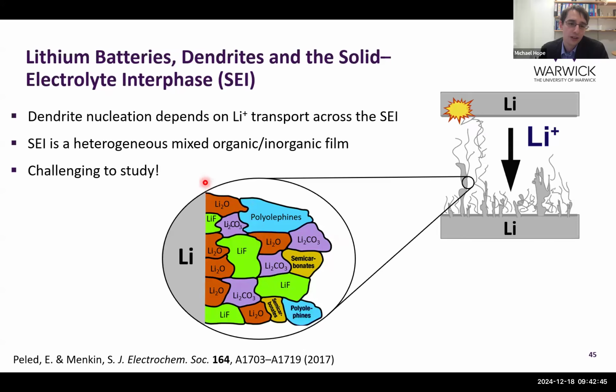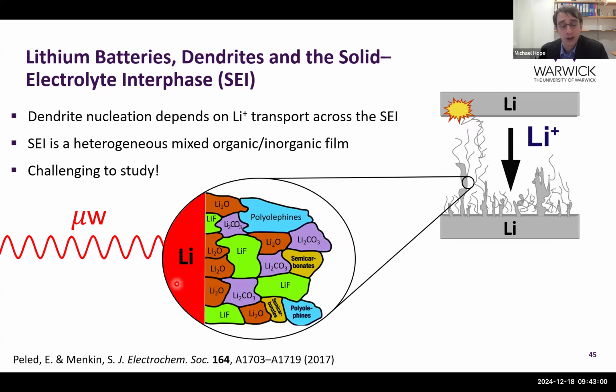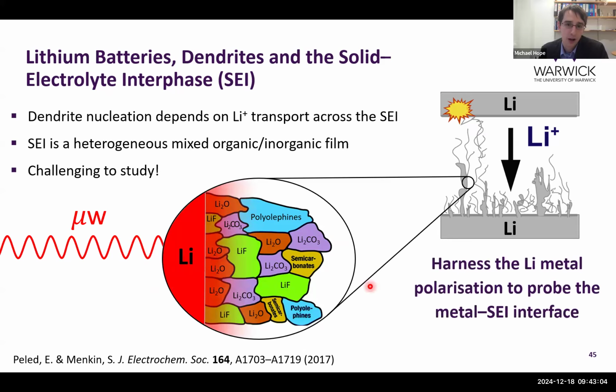And so this is a very difficult system to study. In particular, we want to study this interface between the metal and the SEI, because that's where the dendrites nucleate. And so we're trying to study a buried solid-solid interface. What we're going to do is shine microwaves on our sample, hyperpolarize our lithium, and see how that transfers into the SEI, and harness that DNP of lithium metal to probe the metal SEI interface.